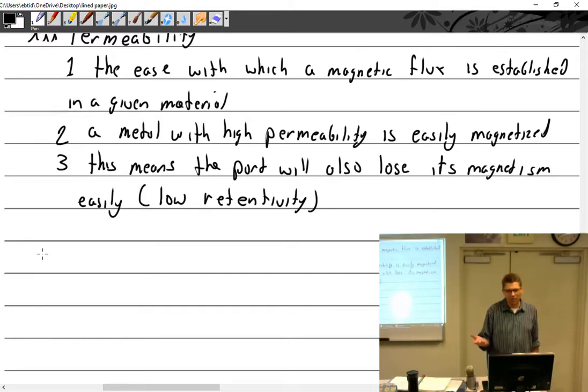You know, we could experiment with that with our Gauss meter. I could show you that while under the magnetizing force, the Gauss is going to be extremely high, and it's going to fall off some. And we'll talk about the hysteresis loop, and that's exactly what that is. So it does get higher while it's being magnetized and drops off to a point. It doesn't go up to this level and stay there. It drops considerably depending on the part.